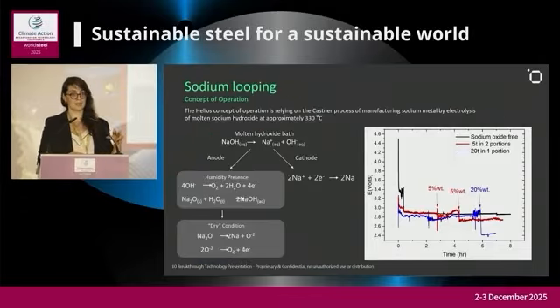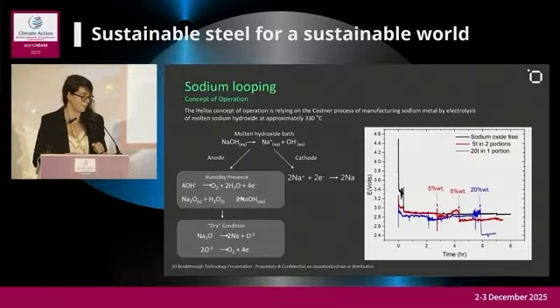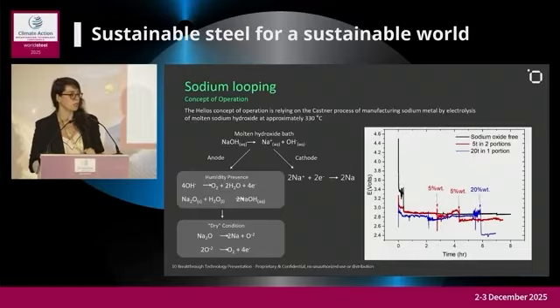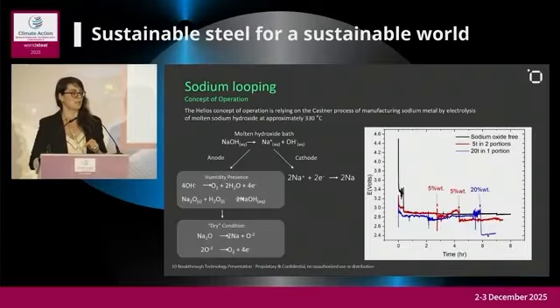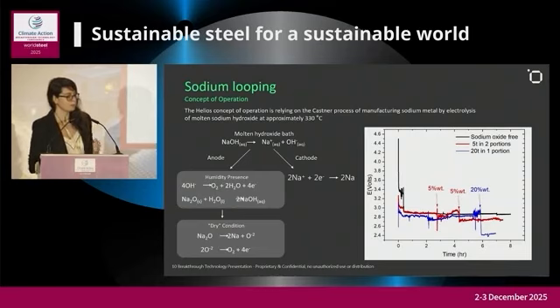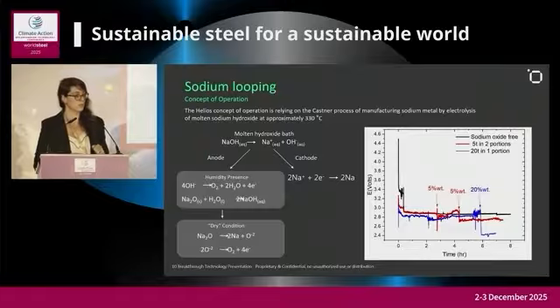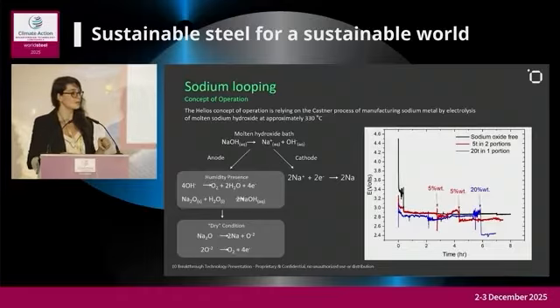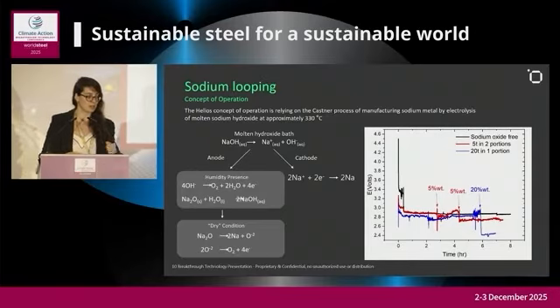So again, after separating the Fe metal from the sodium oxide via chemical separation, we use the reclamation by electrochemical methodology. So this is diving a little bit into the electrochemical cell that we are using. On the cathode side, of course, there is the evolution of the sodium metal. And on the anode side, by using sodium oxide as the reagent, which is the one that the sodium is reclaimed from, there is only oxygen evolution, meaning we are using so-called dry conditions and not hydrogen evolution.